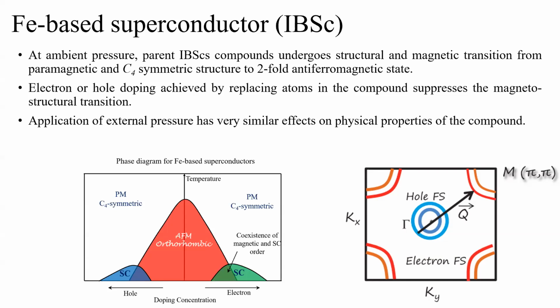Another different thing that these compounds have is the number of hole pockets or electron pockets in the Brillouin zone. In copper-based superconductors, the number of pockets that you have in the Brillouin zone is only one. However, in these cases, you have five pockets. Two are electron pockets centered at the M point, and three are hole pockets at the gamma point. The other hole pocket is not seen here because it is degenerate at this binding energy range, at the Fermi level. Now we also have a Q vector. This Q vector is basically a nesting vector, which is related to this point, in the next few slides.